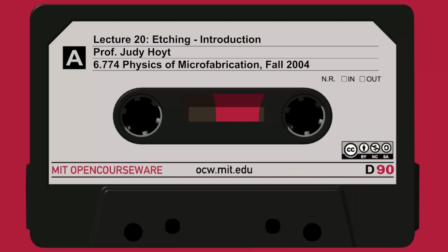So as we move to the bottom of slide 3, as you move from the left, panel A to B to C, you're moving from completely isotropic etching, as you can see by the little vectors here. This particular etchant is etching this material vertically at the same rate it is laterally. Here's a little more anisotropic. The vertical etch rate is faster than it is laterally, but still there's some lateral etching. And this is completely anisotropic. There is no lateral etch rate, only vertical etching. So you're moving from completely isotropic to completely anisotropic, from left to right. So you're getting more and more directionality.